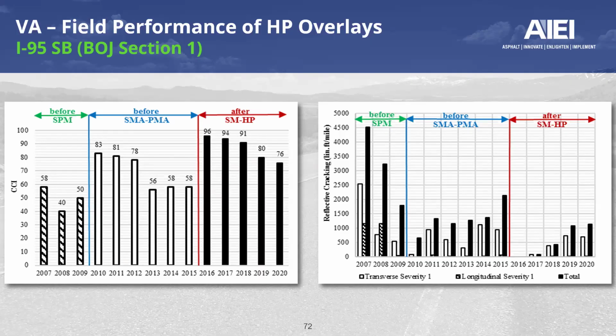Based on the left graph and the collected data, there was a stone matrix asphalt layer, an SMA, built with a conventional PMA binder, compared with a dense graded HP. You will see a much higher Critical Condition Index from construction as well as through the first year of performance. You will notice as well that the decay of the CCI, or the rate of decrease of that CCI, is much slower for the HP layer compared to the conventional PMA.